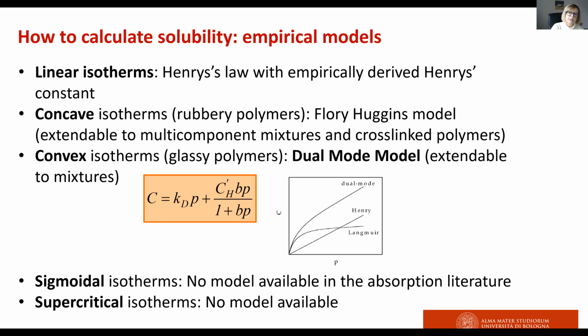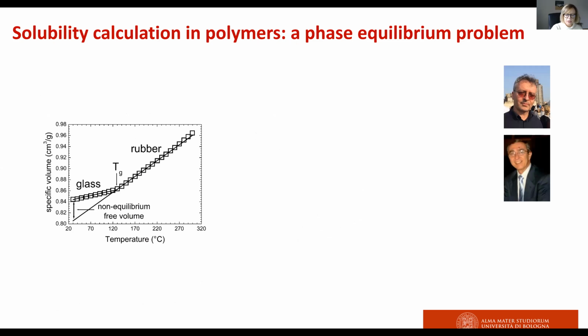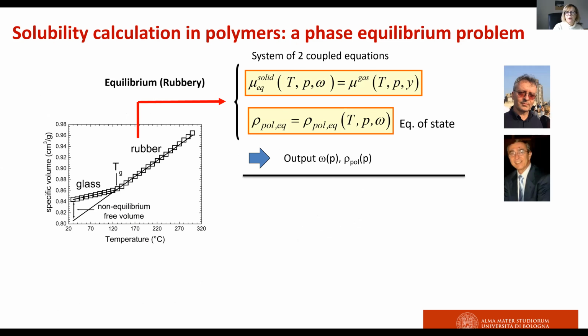More rigorous theoretical models are represented by equations of state, of course, and by a non-equilibrium version, valid for glassy polymers. This approach was presented in the 90s by Professor Doghieri and Sarti, and allows to account both for the solubility in the rubbery membrane, where you actually apply the phase equilibrium condition for the gas penetrant between the membrane and the external gas phase, and you simultaneously solve the equation of state for the gas polymer mixture, which allows you in the end to simultaneously find the solubility and the density of the polymeric mixtures.